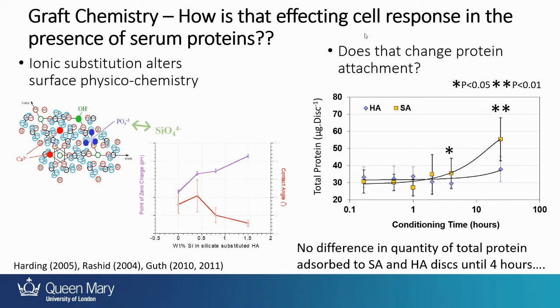So those of you that are good at chemistry will have thought to yourself, they're swapping silicate ions for phosphate ions. They've got different charges. So that's going to affect the charge balance within the material and its electrochemistry. And what that does is it changes what we call the point of zero charge. So effectively, the surface charge of a material when it's put in an aqueous environment is related to its intrinsic chemistry. And by messing around with the ions in the chemical structure of the material, we were basically changing that surface charge on the material. And that was also having an effect on the hydrophobicity of the material.